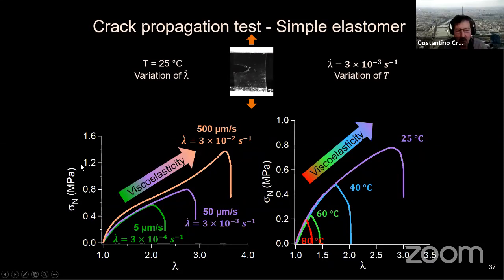So this is now a test on a notch sample. You can see the nominal stress versus stretch, at different pulling rates and different stretch rates. These are nominal stretch rates, so it's divided by the length of the sample. And from this, we can extract the crack velocity. So we can see how fast the crack propagates. It's not constant, but we can have an average crack propagation velocity.